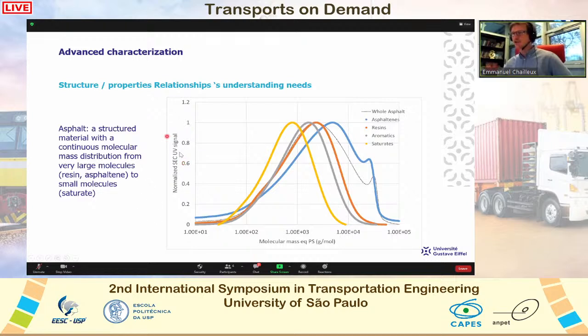So here we have the normalized size exclusion chromatography signal according to the molecular mass equivalent polystyrene for the saturate, the aromatic, the resin, and the asphaltenes. And here the dotted line represents the whole asphalt. So you can see that all these distributions overlap.